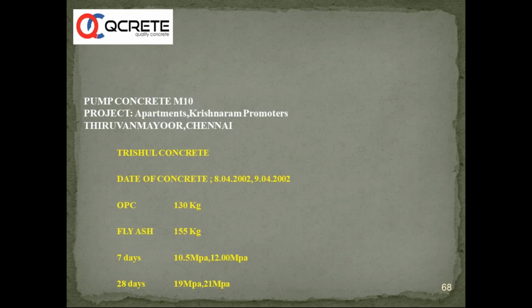So we used the property pumpability to pump the concrete. We made a M10 mix where the concrete had to be pumped for M10 concrete for a PCC for a particular customer in Chennai, where the OPC mix was 130 and fly ash mix was 155 kg, and you can see the strengths actually. So whenever we used to have long horizontal pumping or higher vertical pumping, we used to use fly ash as a pumping aid actually. So the cohesivity, the pumpability of the mix was completely increased by usage of fly ash.